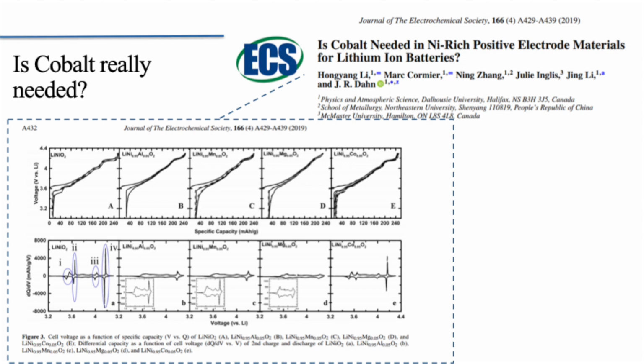And if you have pure nickel, you will see these spikes. These spikes are detrimental for the stability of the cathode and long cycle life, so you need to reduce these peaks. All right, you don't see many peaks if you have nickel and aluminum. Nickel and manganese, there are not many peaks at all. And nickel and magnesium, that's fine. And nickel and cobalt, you still have a peak, and that's not good.